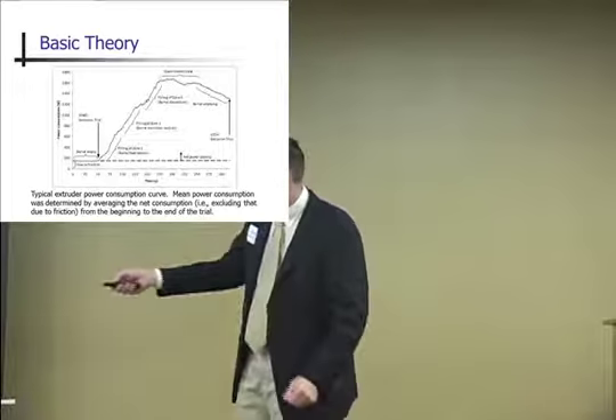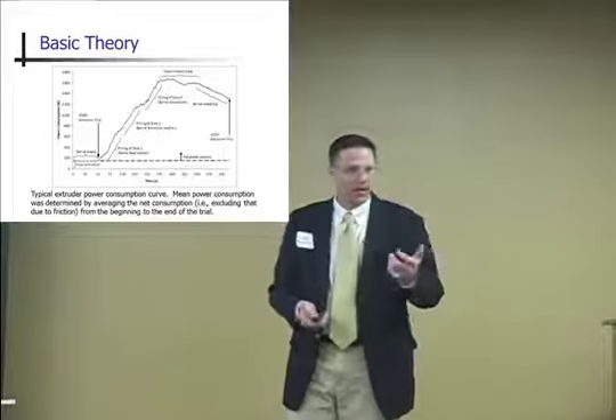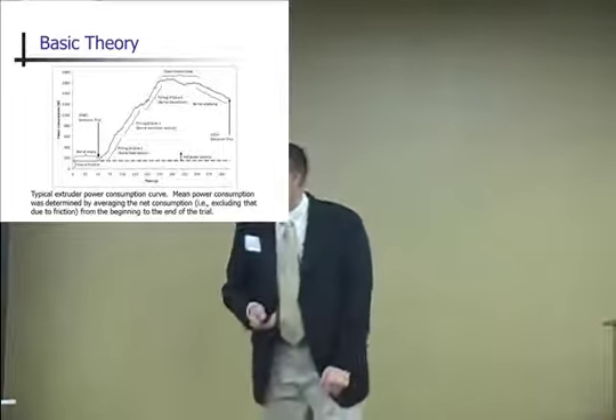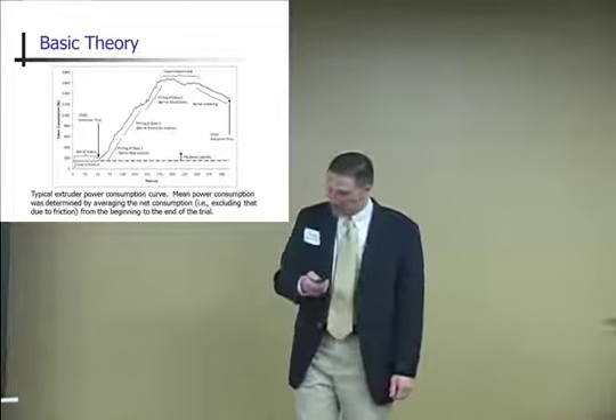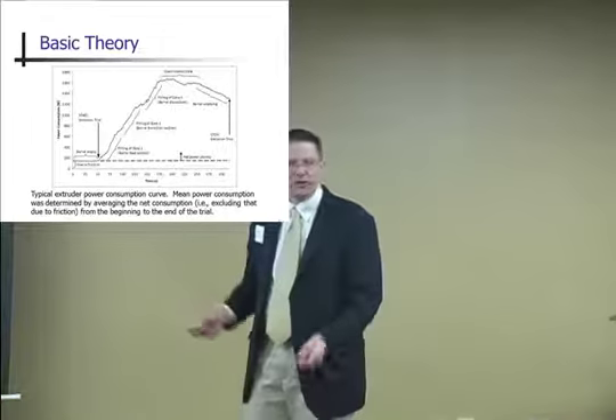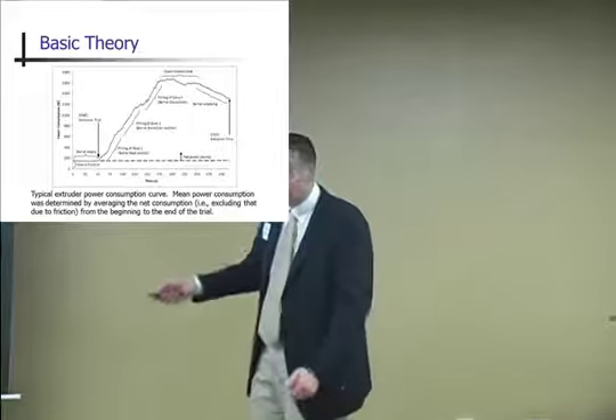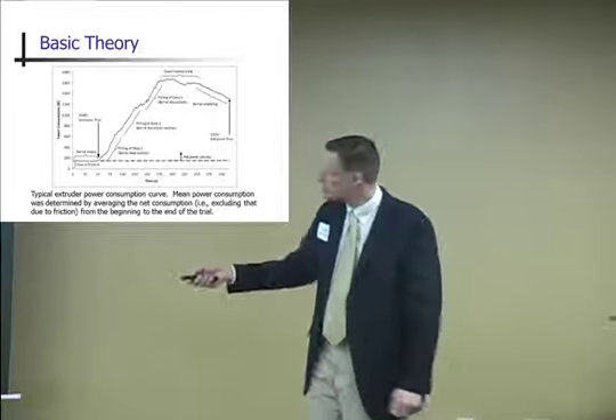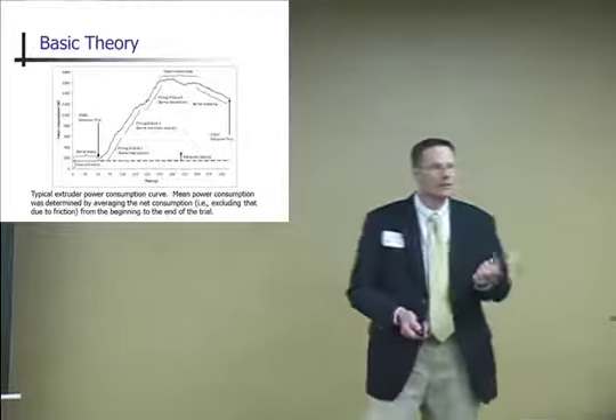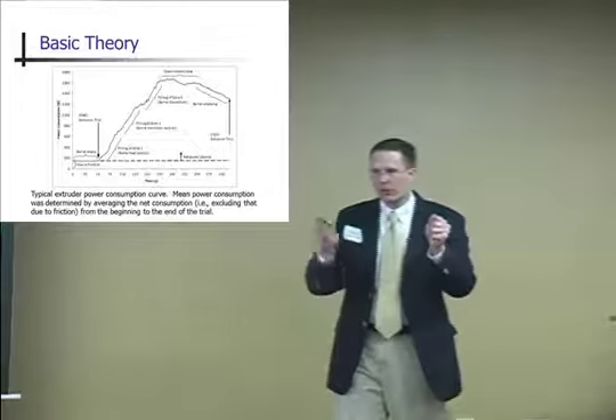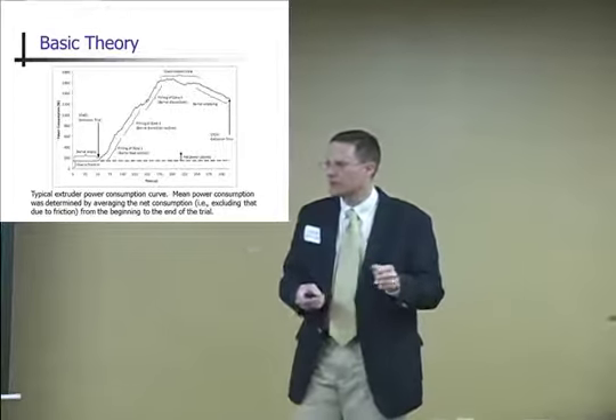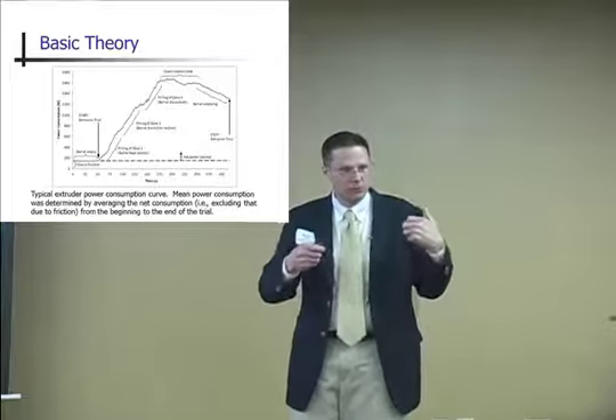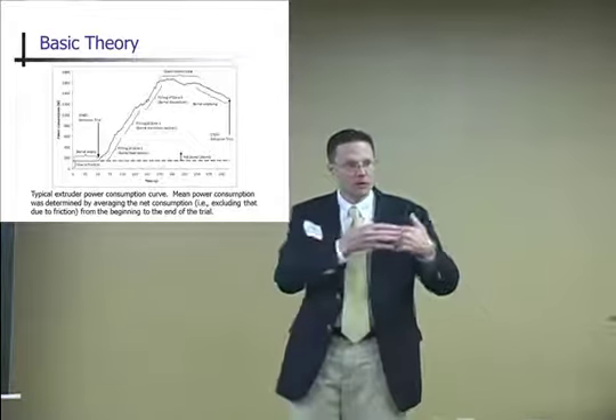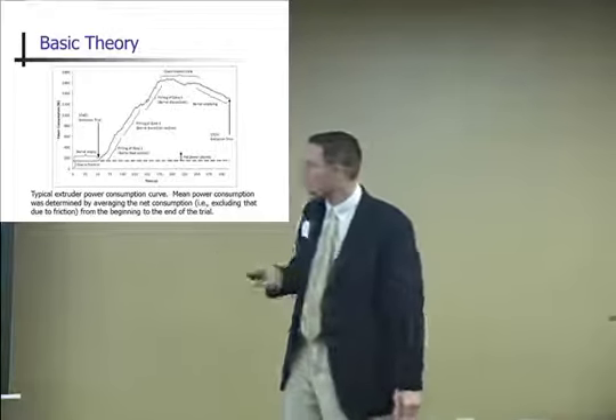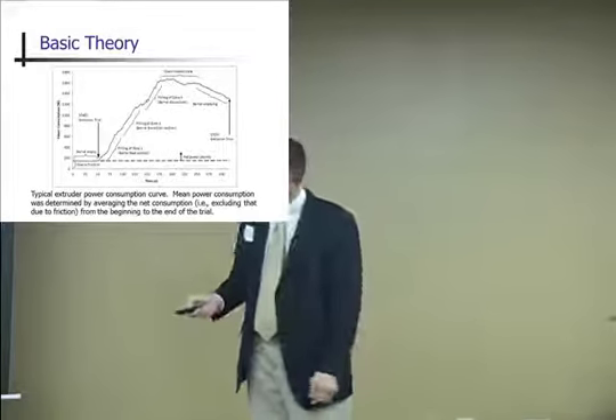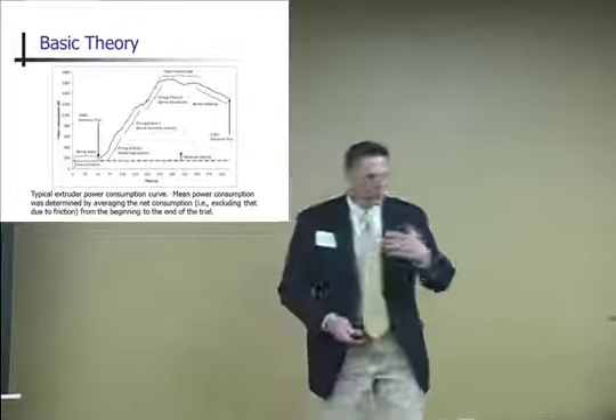So you measure it with one of the three-phase power meters, which you can get for about $2,000. Now, they used to be a lot more expensive. So you measure that. Here's your power consumption. Divide it by your mass flow rate, which you measured with your bucket. And this gives us what's called the SME, specific mechanical energy. How much power per kilogram or per pound. So the more power it takes to push that material through, the more energy you're adding into the friction, into the heating.